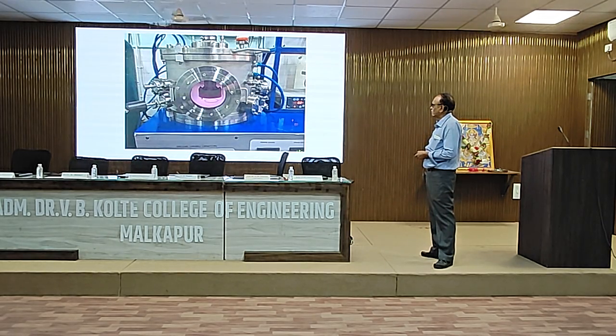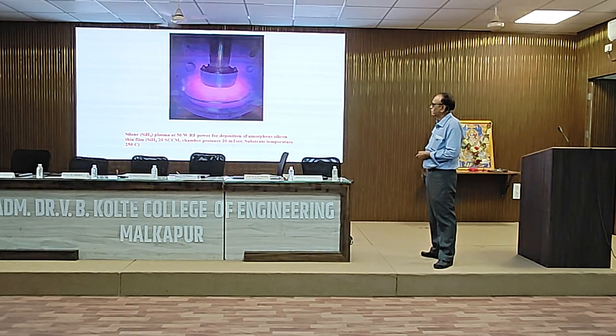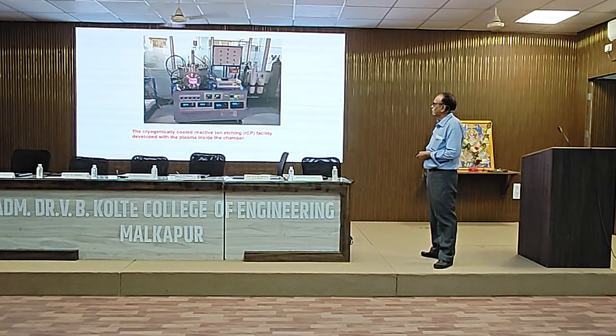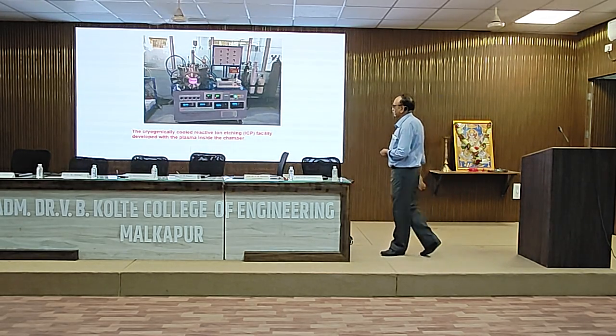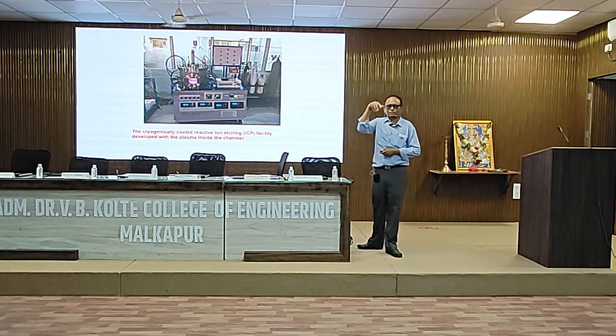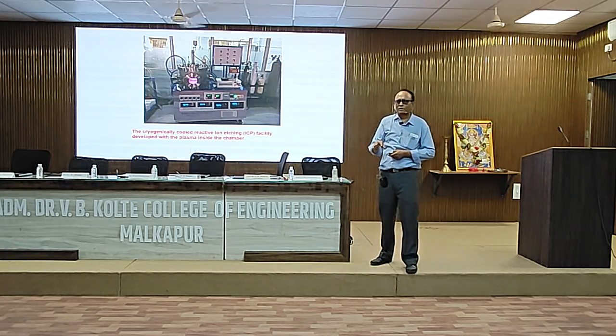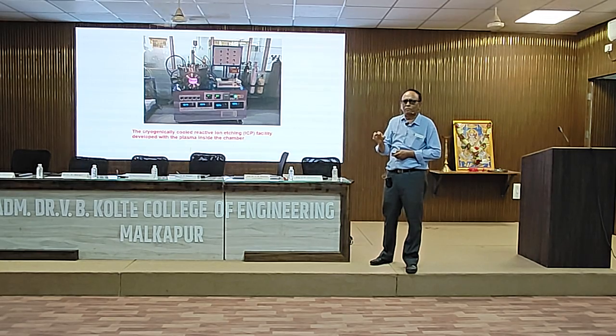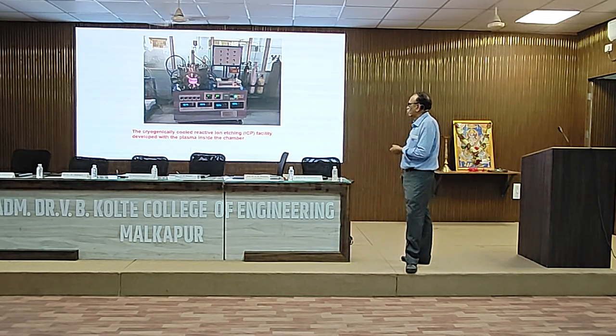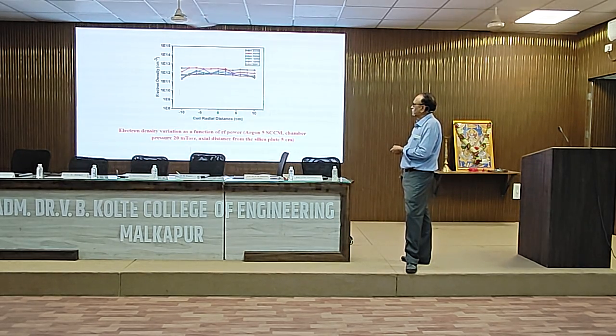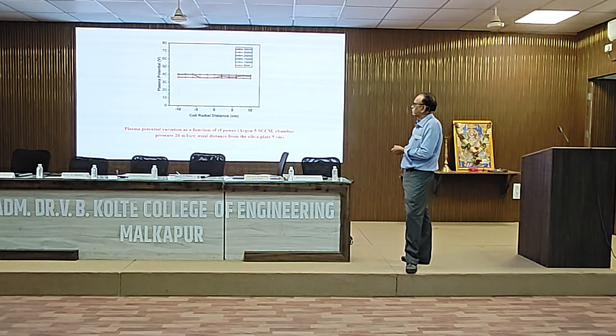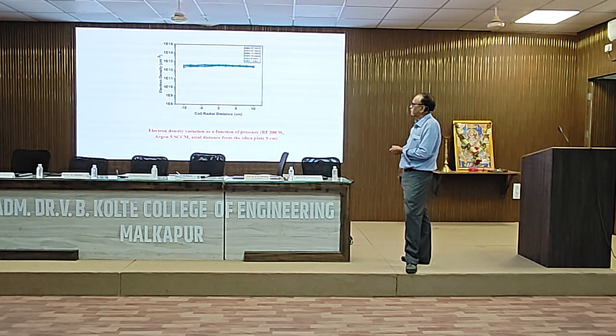Okay, this is how your plasma looks like. 8-inch diameter of silicon wafer can be processed for solar cell deposition, etc. Amorphous silicon again. There is another unit that is developed for reactive ion etching, because when you want to make the MEMS, etc., you need to etch those silicon wafers. So this cryogenically cooled reactive ion etching facility, a similar version of what I have shown you earlier, is developed. These results are only to show you how uniform the plasma parameters are.